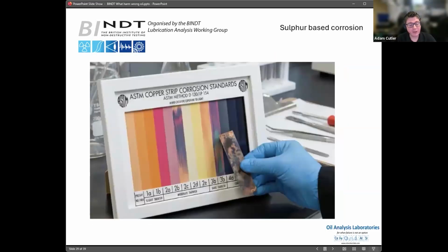And the way we measure this in the lab is we do a copper corrosion test. So we simulate that environment and we take a copper test strip and see how much tarnishes. You can see this specimen here is actually not looking too healthy compared to, on the left-hand side, what a nice, fresh, healthy specimen should look like.